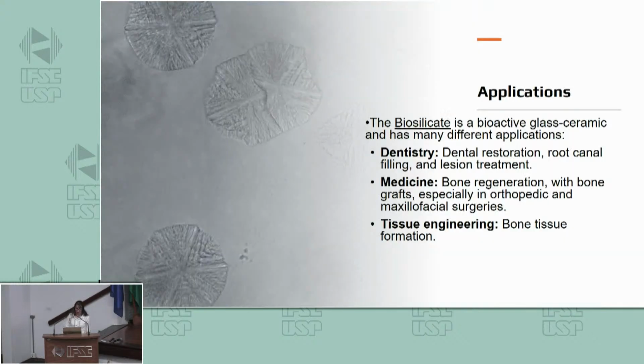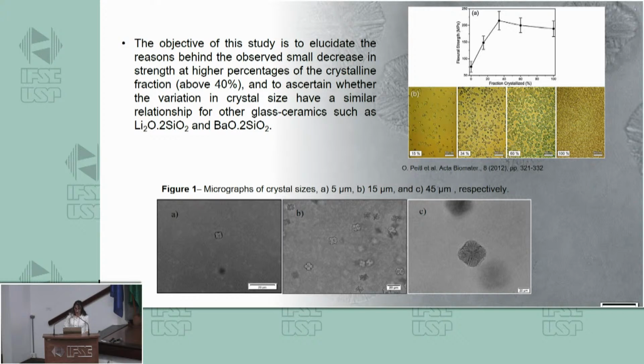The biosilicate is a bioactive glass ceramic with application in dentistry and medicine, especially bone regeneration and tissue engineering. The objective of this study is to elucidate the reason behind the observed small decrease in strength at higher percentages of the crystalline fraction, and to ascertain whether the variation in crystal size has a similar relationship for other glass-ceramics, such as lithium silicate and barium silicate.